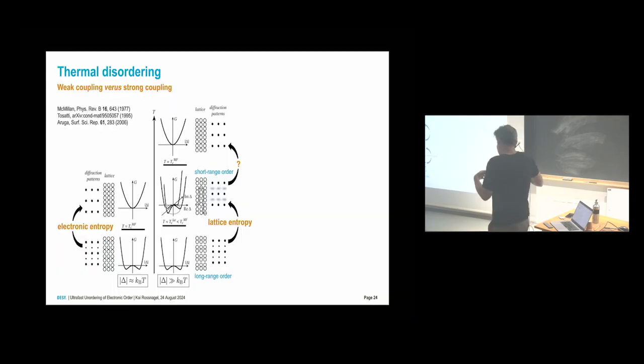Okay, then now we come to this unordering. How do we want to do this? Come back to this thermal picture. Again, weak coupling, charge density wave, thermal excitation of electrons across the gap. And here in this strong coupling, you have lattice entropy. So electronic and lattice entropy, electronic and lattice disorder play an important role.